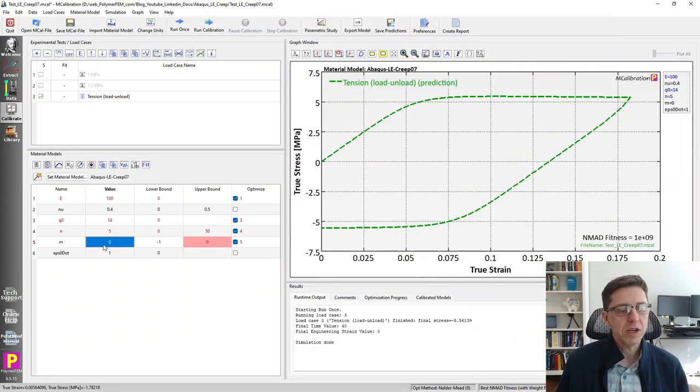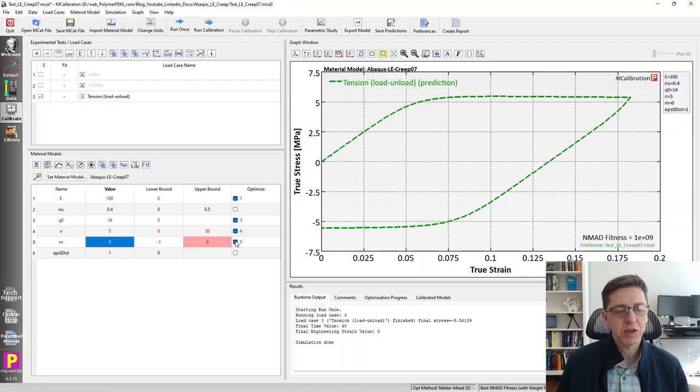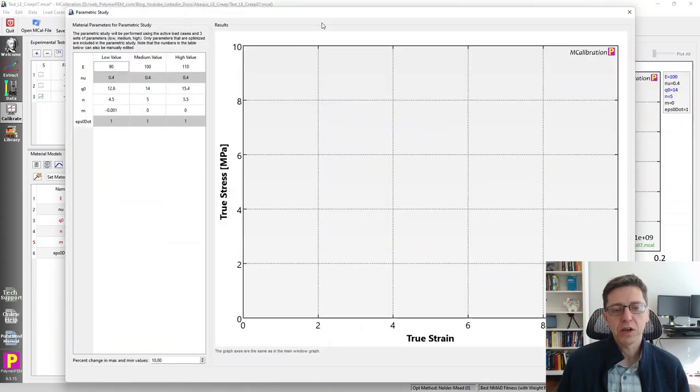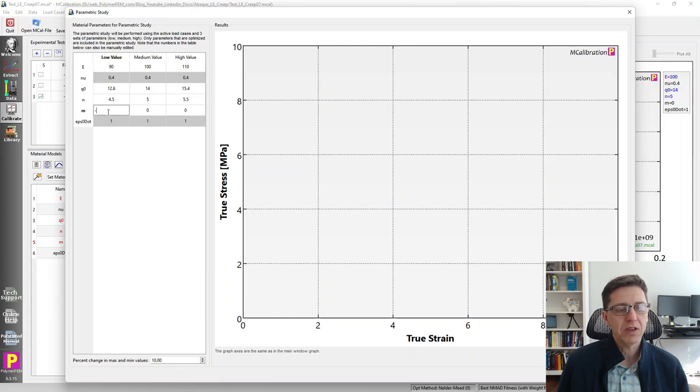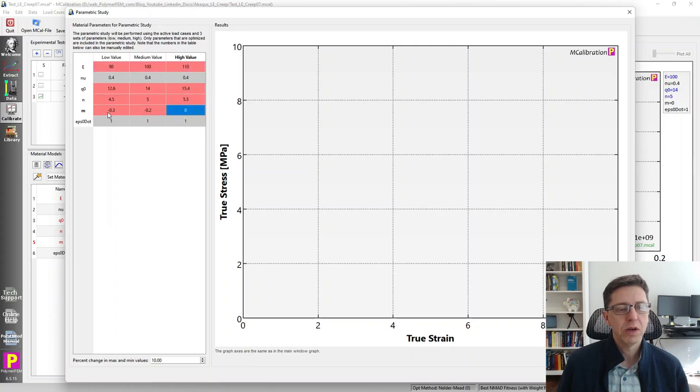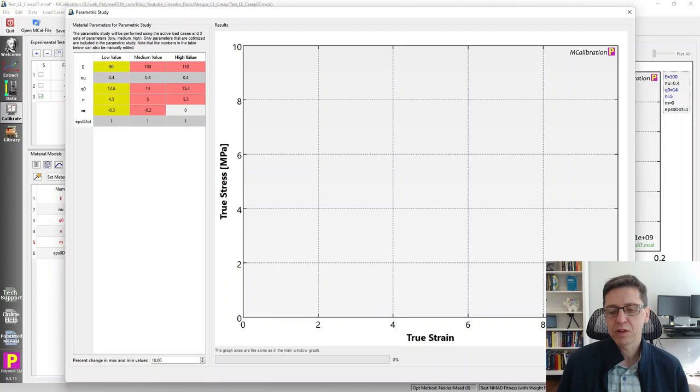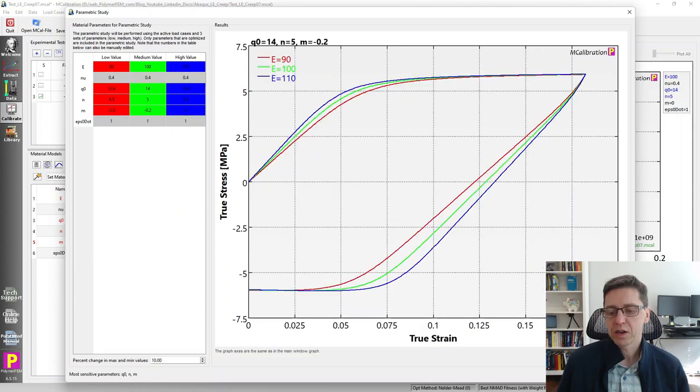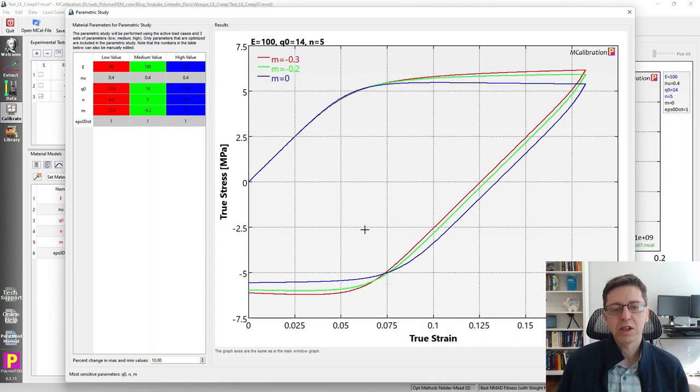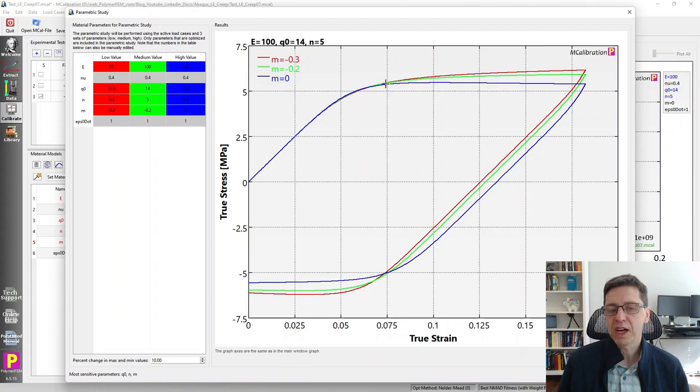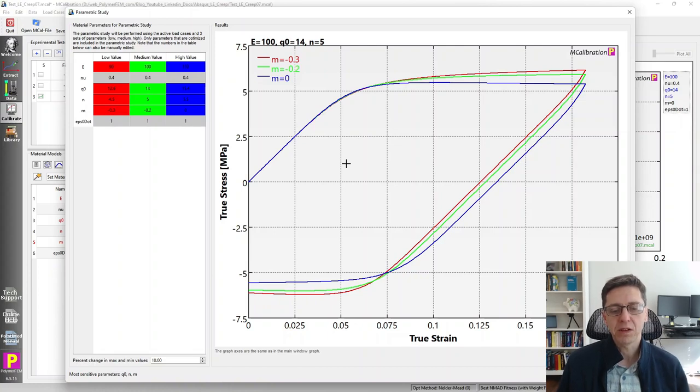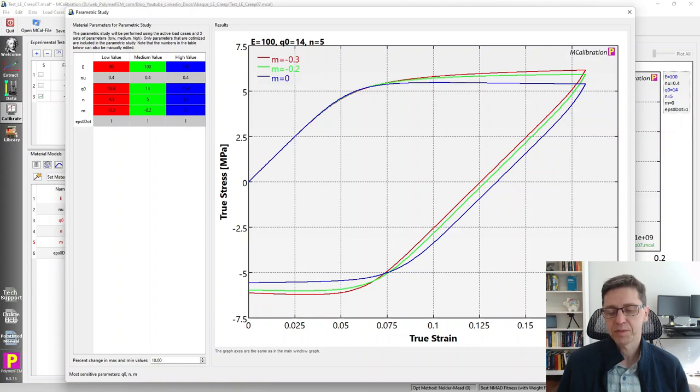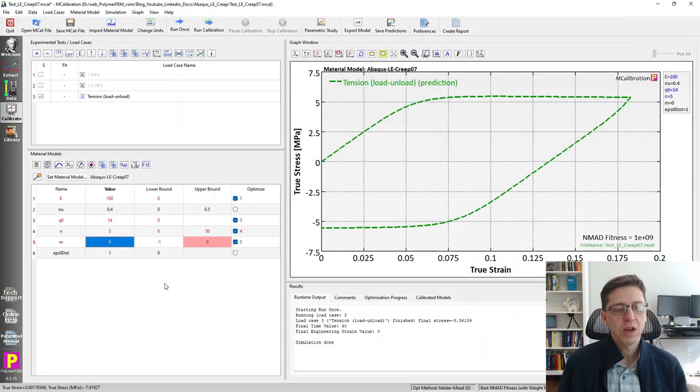To study the influence of the M parameter, we need to activate it as an optimized parameter, otherwise we can't get to it. So I'm going to turn it on, go back here. I'm going to make these M parameters which have to be larger than minus one and less than zero. So I'm going to do minus 0.3, I'm going to do minus 0.2, and I'm going to make it zero perhaps. So evaluate this one and I'm going to click on M and we'll see that the M parameter changes the slope after the onset of creep here. It makes the creep resistance strain dependent and that's the purpose of that. But it does it in an interesting way as you can see here. So that's the influence of those parameters.